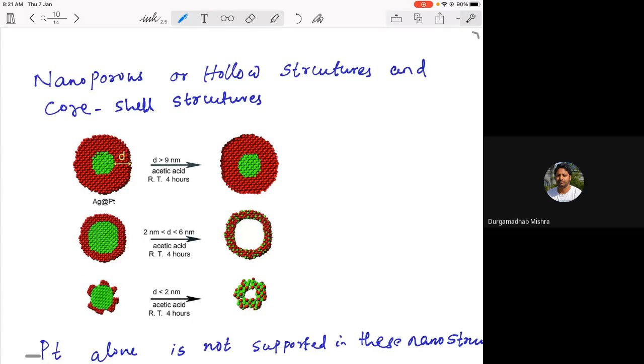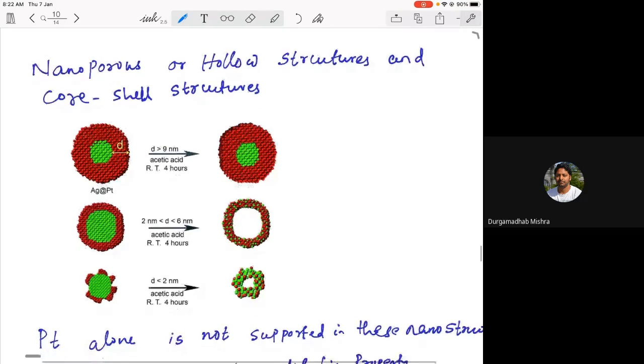Here a core-shell structure is used, with a silver core and platinum shell, and then they used an etching technique, mostly acetic acid in an oxygen atmosphere. So you can differentially etch the core, the silver, and what remains is a hollow nanostructure with platinum. Maybe during this etching process some silver diffuses into the lattice of platinum and remains there, and this is what you get, a hollow